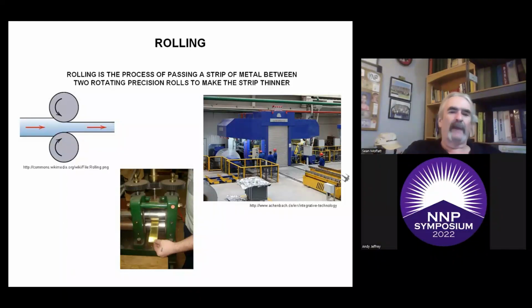And basically, you're passing your strip through a pair of rolls that are turning, and what you're doing is reducing the thickness of your strip. Interestingly enough, the strip doesn't really get wider, it just gets longer. So you can have a 5-foot piece of strip, and if you're going to reduce it down 50%, that strip's going to end up being almost 10 feet long by the time you're done.